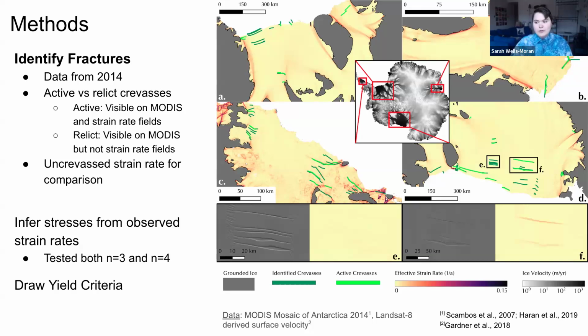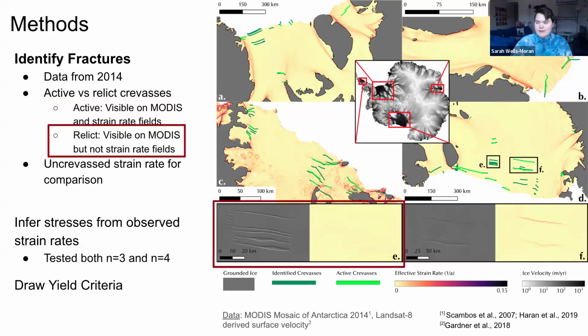These fields are all from 2014. As an example of active crevasses, this box shows a region on the Ross ice shelf where the rifts are visible very clearly on the strain rate imagery and also on satellite imagery. And here is another example, just adjacent to those fractures on the Ross ice shelf, where a lot of crevasses are visible, but there's no evidence of them in the strain rate field. So these crevasses may have formed upstream and then advected downstream into stress states that aren't associated with formation. We wanted to make sure that we were looking specifically for active crevasses to get that clear delineation.